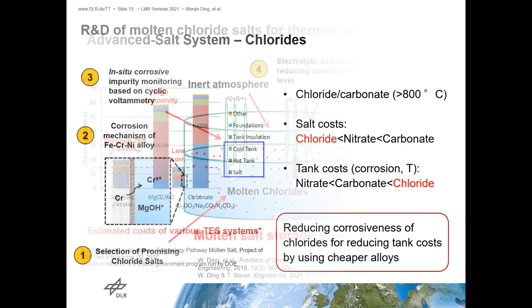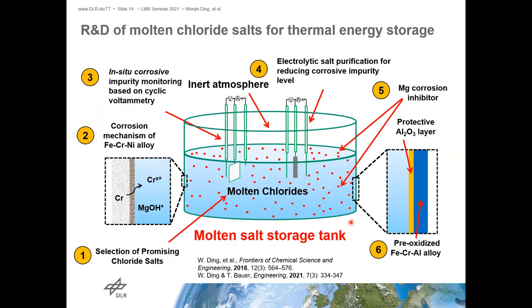So in our group, we have done systematic research on molten chloride salt for heat energy storage. First, we selected the promising chloride salt mixtures, and then we studied the corrosion mechanisms, and also we developed corrosive impurity monitoring technologies based on the electrochemical method, and also used the electrochemical method to purify the salt to reduce its corrosivity, and also added some corrosion inhibitor to reduce the corrosivity of the salt, and also develop new structural materials.